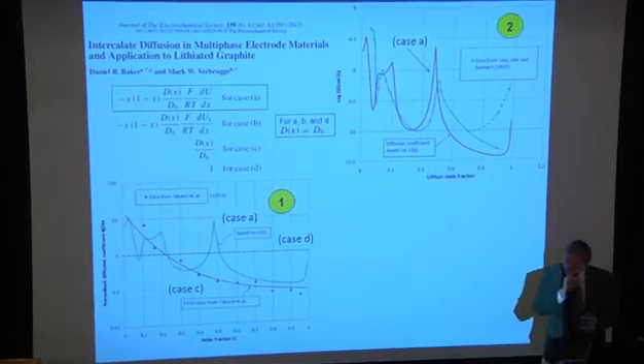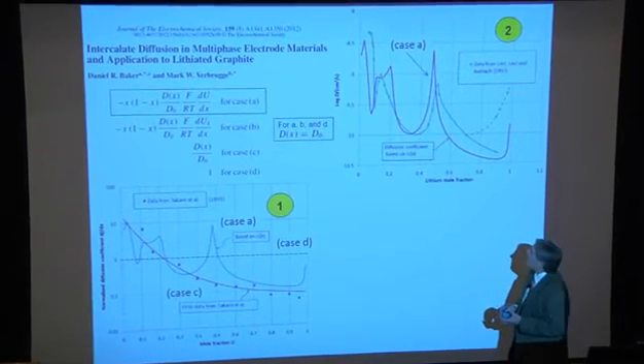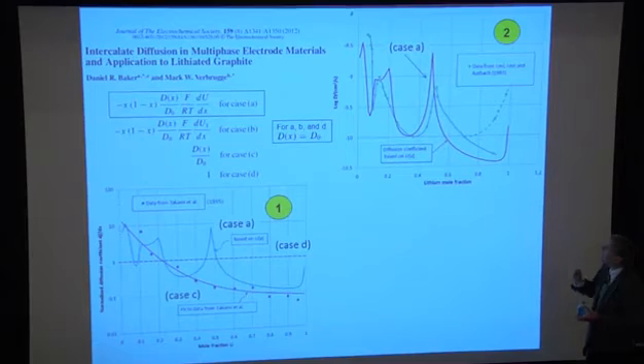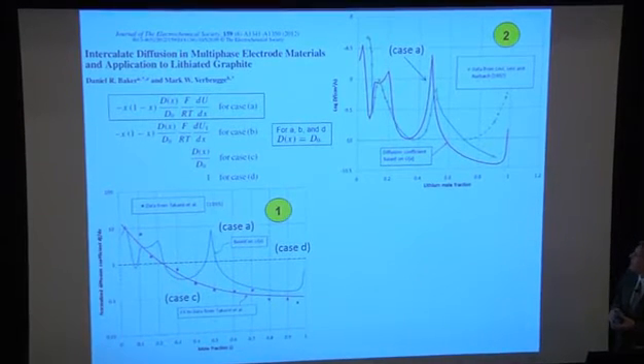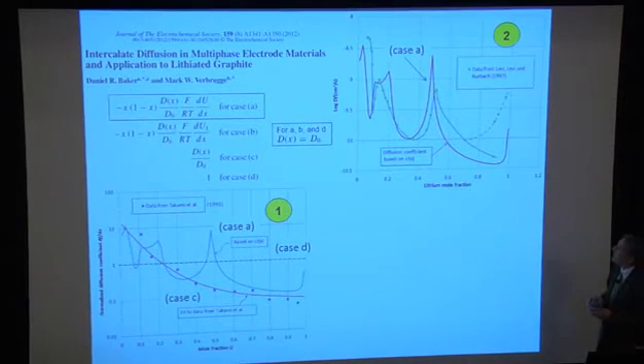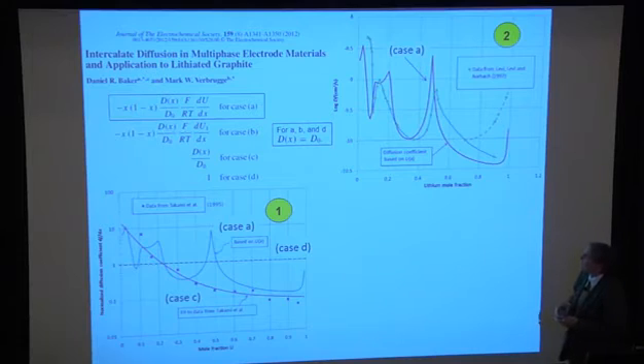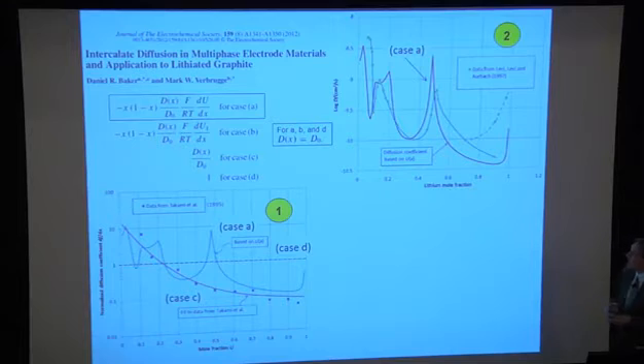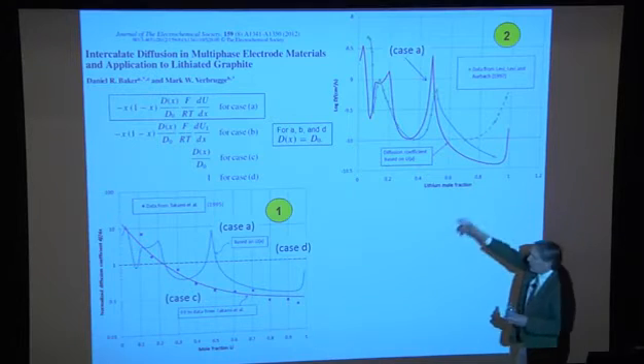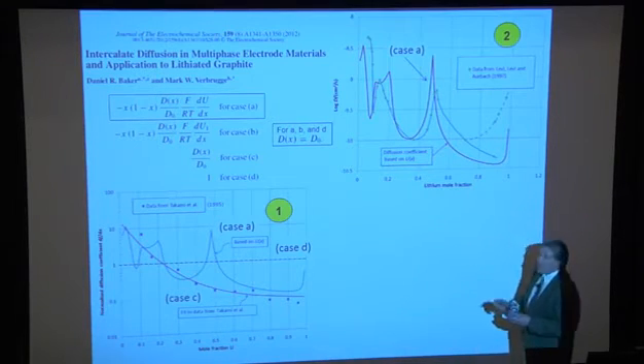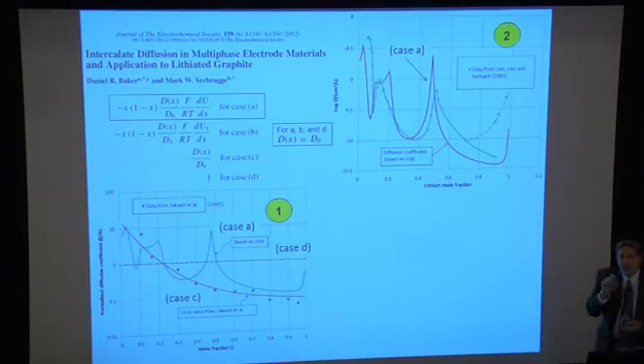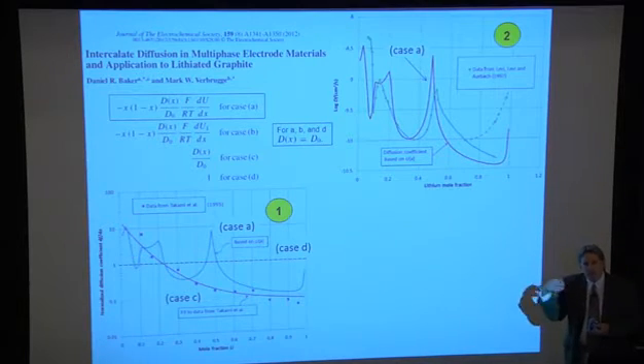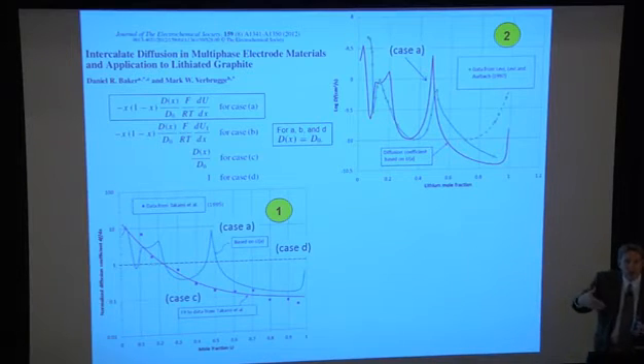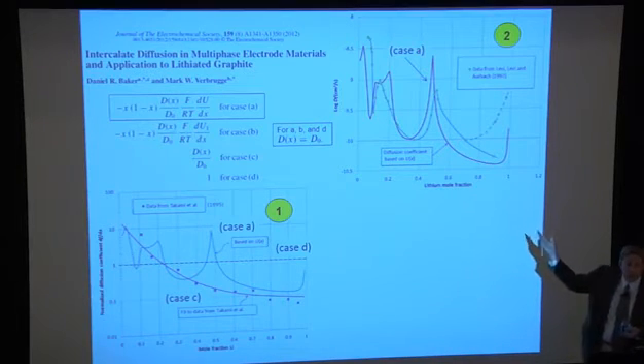So it was just amazing to me when I saw this publication later by Aurbach, and it was an older publication, I just hadn't been aware of it, where they had taken some very careful PITT data, potentiostatic intermittent titration technique, and the symbols are their data, the blue lines are drawn through their data, and the red curve shown here is actually the blue curve over there, but you can see it matches up pretty well. And the idea is that the irreversible thermodynamics that comes from the open circuit potential embedded in the transport equations gives rise to an effective diffusion coefficient that looks a lot like what people measured.